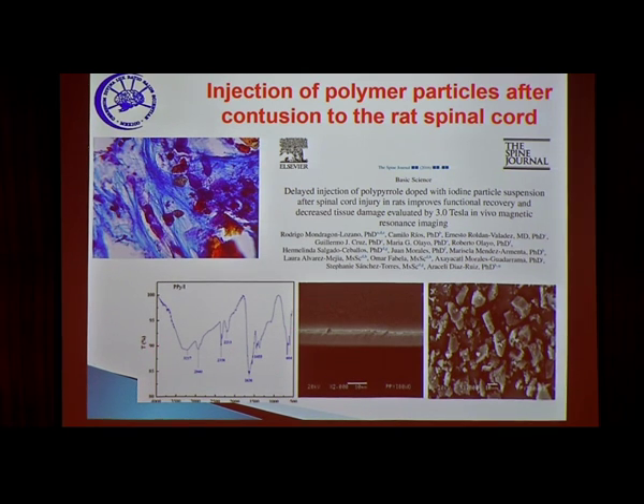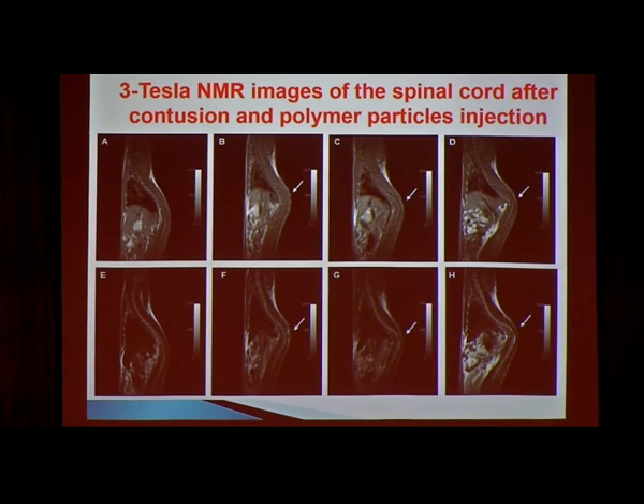So this is the infrared spectrum of the particles. And for the evaluation of the success of this injection, we use nuclear magnetic resonance images in a commercial 3 Tesla equipment from our hospital, and we were able to locate with these images the site of the lesion. This is the control rat receiving no particles of the polymers, and you can see here in the lower lane the images from several rats receiving the trauma, and then 48 hours later the injection in the spinal cord of the polymer particles.